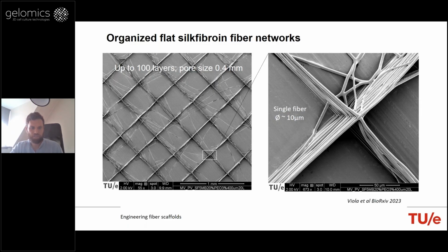Of course, there is always some misplaced fibers that were hard to control, but this is also due to the nature of the natural polymers that are quite tedious to work with, and it's not always easy to control their properties, even if you control all the extraction process and all the processing conditions. So there is always some heterogeneities in your ink and in the environmental conditions that led to these misplaced fibers. But overall, we were quite pleased to see that we could achieve flat constructs with a square-shaped architecture